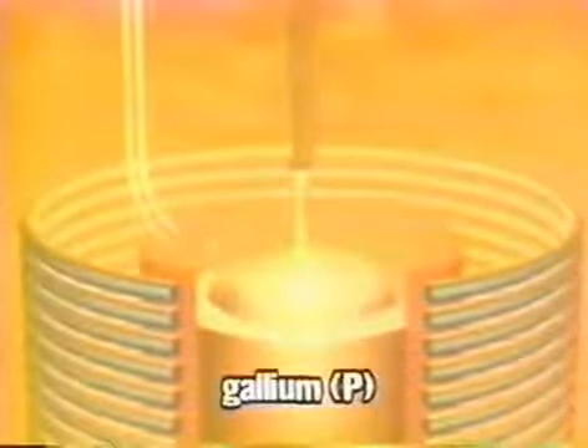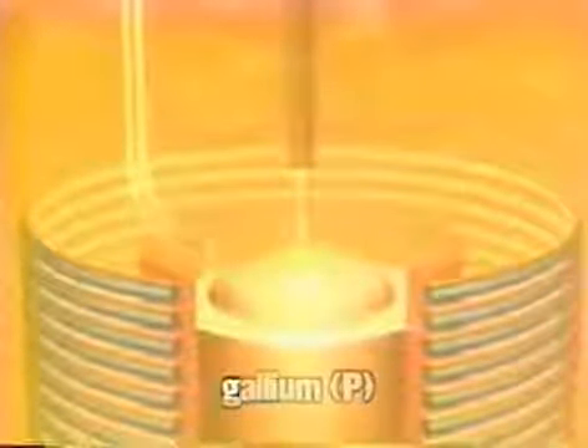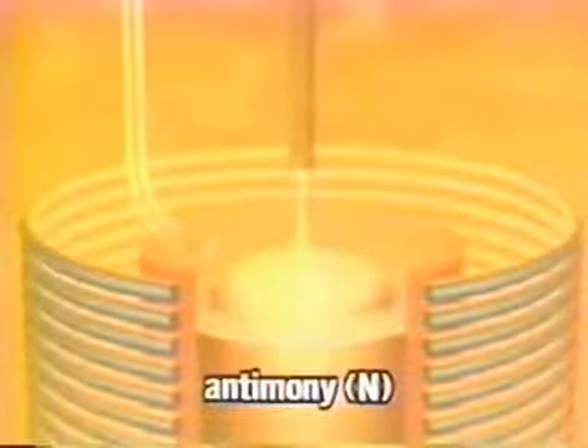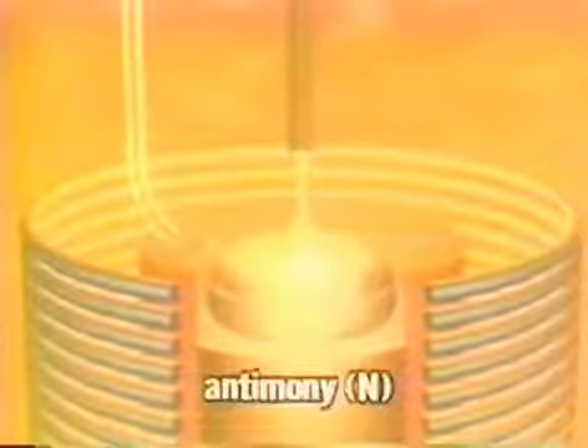Here's how grown transistors are made. During seed crystal production, P-type impurities, in other words, electrical elements with positive properties such as gallium, are dropped in. The gallium then forms a melted-in layer in the growing crystals, which become a P-type layer. After about 10 seconds, N-type impurities such as antimony are then dropped in, so that another N-type layer is grown below the P-type. The crystals thus form an NPN sandwich.